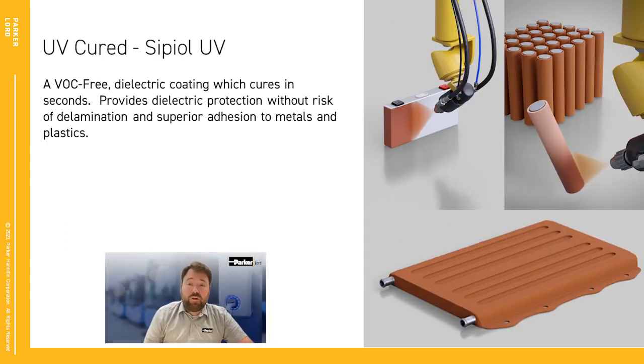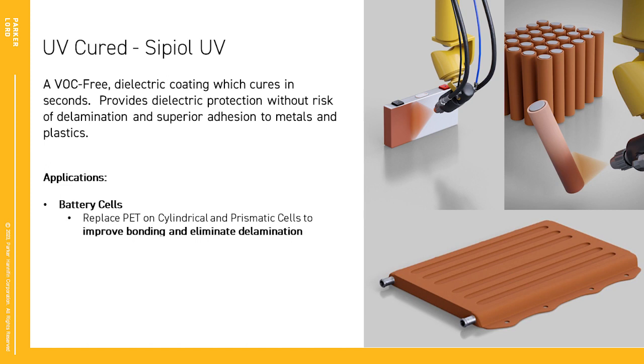Sipiol UV is our UV cured dielectric coating, which cures in just a couple of seconds. It benefits from being 100% VOC free and also being spray applied with standard spray equipment. It targets very similar thin application thicknesses like JMC. It was also developed as a replacement to PET films, which are expensive to automate, tear easily, and generally have low adhesion to the substrate and other adhesive materials used in conjunction.